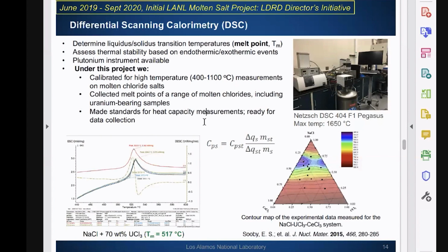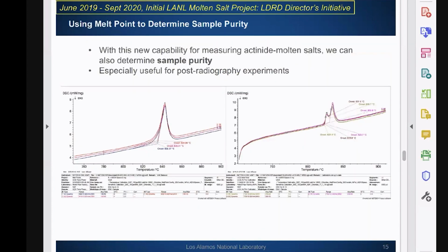Another kind of neat thing that came about with this work is that we can also use it for purity measurement. And so I really appreciated what Melissa was saying too about quality of sample. And this just kind of shows a nice, neat example about that. On the left here, we have a very nice clean sample of uranium trichloride, and the one on the right is not so pure. And so we use this as one of the many ways to make sure our samples are pure, and it's especially useful for our post-radiography experiments. We can bring in our samples and make sure they're still pure and they're still what they were when we put them in.